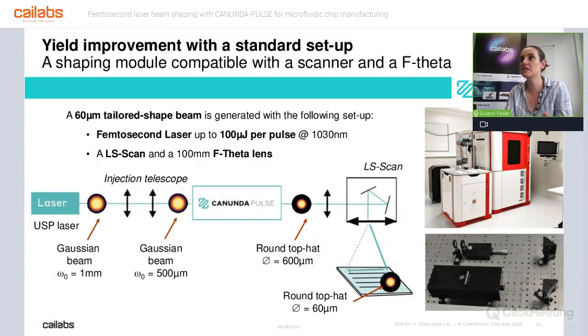I think it's a good start to explain how our module is installed and used inside one of the LASEA machines. You have a laser. In this case, it's a femtosecond laser from Amplitude delivering 100 microjoule per pulse at 1 micron. Then you have an injection telescope, made to adapt the beam waist to the proper dimension inside our CANUNDA-PULSE module. After that, our module delivers a round shape of 600 micrometer diameter. It goes through an LS scan from LASEA and a 100 millimeter F-theta lens. You then have in your processing plane a 60 micron diameter round shape.